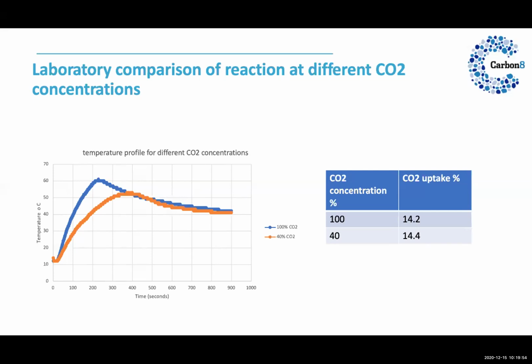So if you have too high a temperature, the CO2 solubility is reduced, so the reaction is reduced. So actually, if you can control that exotherm, you get a much better process. So this is just a couple of runs in the laboratory to compare the reaction at different CO2 concentrations. So the blue line is 100% CO2 and the orange line is 40%. And you can see how the exotherm is reduced and also delayed, so that in your full-scale plant at 10% CO2, the exotherm is very much more controlled, and we don't have so much of the problem of that heat.